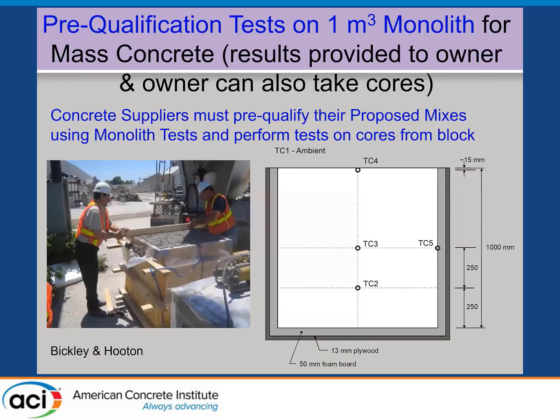Now, for pre-qualification tests, John Bickley and I worked on several big projects, and it's been used in a number of projects since then, using what they call monolith tests for mass concrete or other large elements. Because of the high cement contents that are used now, even small elements, less than half a meter in cross section, can be considered mass concrete because of the amount of heat that's generated. But we cast these elements in 1 meter cubes, insulated with 2 inches of foam insulation inside plywood. We preset thermocouples and we cast the concrete, and concrete suppliers have got to pre-qualify their mixes, and they do that. The one cube here is the one they're just finishing off now. And we monitor the temperature profiles that develop and do the pre-qualification testing on these blocks.